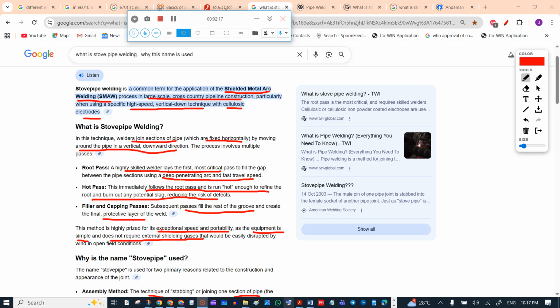A skilled worker lays the first and most critical pass, the root pass, to fill the gap between the pipe sections using a deep penetrating arc and a faster travel speed. Then the hot pass immediately follows the root pass and is run hot enough to refine the root and burn out any potential slag, reducing the risk of defects. Filler and capping passes, the subsequent passes, fill the rest of the groove and create the final protective layer of the weld. This method is highly prized for its exceptional speed and portability.